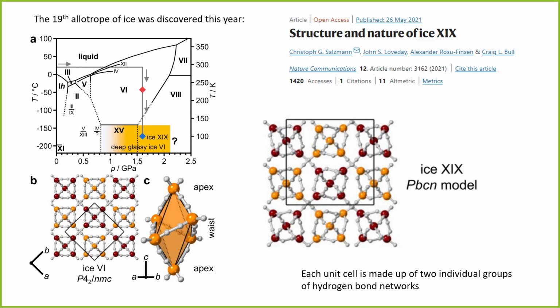So let's see how they've actually created this. I find this very interesting. All right, so they start with liquid at about 25 C, right? So they start with liquid water, and they pressurize the liquid water at isothermal conditions to about 1.7 gigapascals. That's a lot of pressure, as we saw in problem set 1. So they pressurize the water in an anvil cell and there's so much pressure that the water condenses into a solid, and at 300 Kelvin, you're not getting hexagonal water, because hexagonal water at that high pressure doesn't exist.